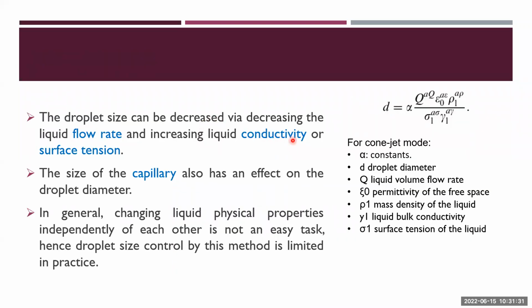So the droplet size can be decreased usually by decreasing flow rate, conductivity, and surface tension. Basically, we don't play much with the conductivity and surface tension, because we just fix them in the formulation, but we play with the flow rate. The size of the capillary also has an effect, but usually after primary experiments we fix the capillary. The capillary here is basically a needle similar to the one used in a syringe, but it's a blunt one, not sharp.